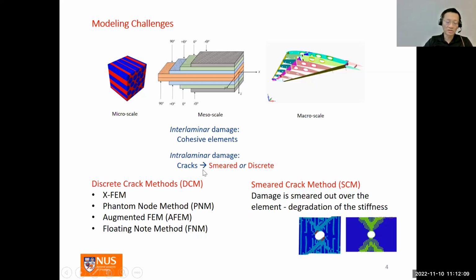Okay, so the discrete crack models cracks explicitly by splitting or partitioning the finite elements, but that comes with a high computational cost. Examples of these include the XFEM, the phantom node method, the augmented finite element method, and something which we developed with a group here in collaboration with Professor Pinho from Imperial, the floating node method. Also, an alternate method is the smeared crack method. This is probably older than the discrete crack method. Here, the cracks are modeled with a reduced stiffness in the finite element. So this is more efficient, but suffers from possible mesh dependency and convergence issues.